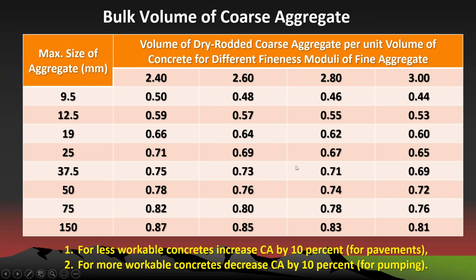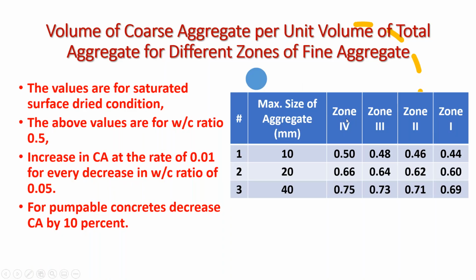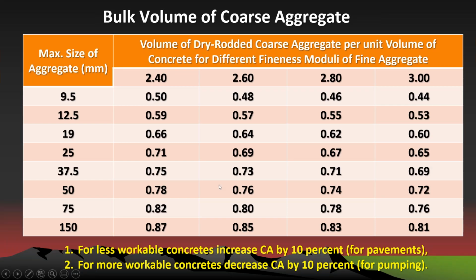The volume of the aggregate, the bulk volume of the aggregate, for different sizes of aggregate. And instead of expressing the fineness modulus like that, we have expressed it in a different way. Instead of fineness modulus, we have expressed zone 4, zone 3, zone 2, zone 1. And as per the ACI method, these values are for the bulk volume of the coarse aggregate, for different maximum sizes of aggregate and different fineness moduli.